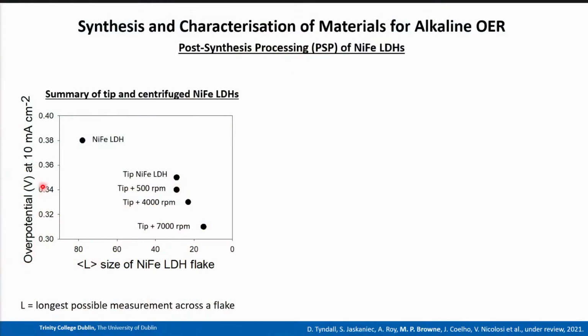So just to summarize then, if we plot overpotential at whatever current density you like, so we pick 10 milliamps per square centimeter, which is the benchmark used in the literature, you can then plot the size of your flake, which is the longest possible measurement across the flake, against your activity. So what we essentially see is that your as prepared material has the worst OER activity in this study. Then once tip sonication is used, you get better OER activity. But then once you size select your materials, you can see this enhancement in the OER once you use higher rotation speeds.